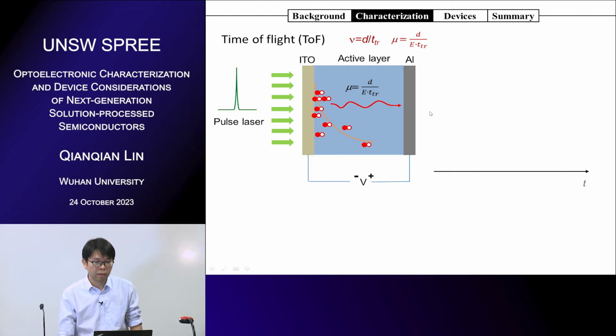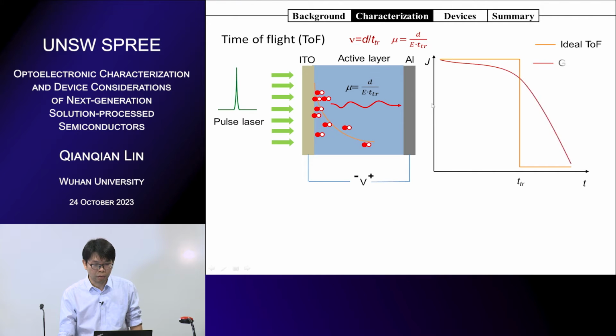This is the basic definition of mobility, and we can measure it if we have a very fast oscilloscope. So ideally, for TOF measurement, we can get an ideal TOF like this. If all the carriers reach the counter electrodes, we can get a transient time. This is very ideal. At least I have not seen such transients. And this is a more real or good TOF. So if you get a TOF like this, it's good.